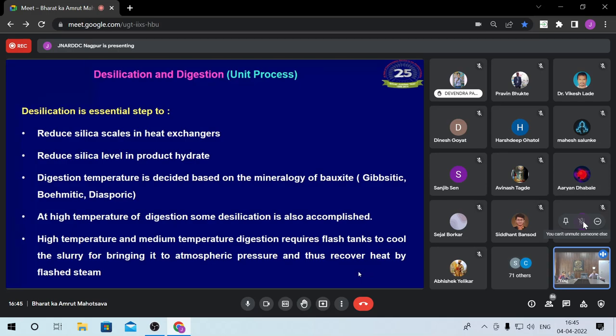In the desilication and digestion, as I told you, to reduce the silica scales, you have to go for desilication. And the digestion temperature, as I told you, depends on the mineralogy of the bauxite. If it is a gibbsitic bauxite, you require a temperature of 107 to a maximum of 145. If it is a boehmitic bauxite, you have to go to a temperature of 240. And if it is a diasporic bauxite, which is available in Jammu and Kashmir and mostly in China and USSR, a lot of diasporic bauxite is there, then you require a temperature of around 270 degrees.